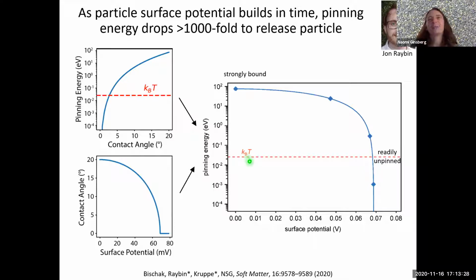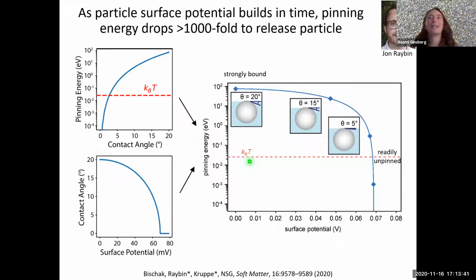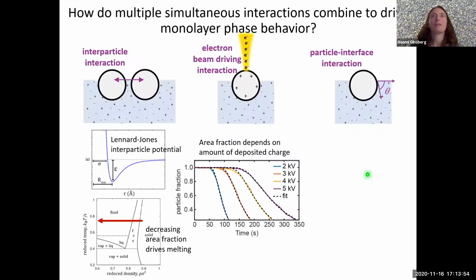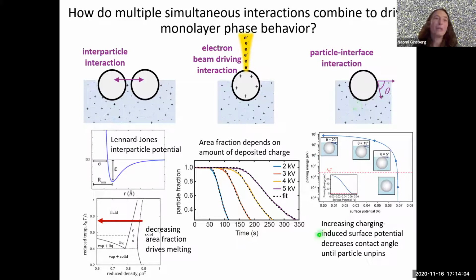And as the electron beam repeatedly scans over a given particle, the surface potential increases, drawing more ionic liquid to cover the exposed particle surface and decreasing the contact angle. And then at a certain point, the pinning energy is decreased so much so that it's comparable to this thermal energy, and it's readily unpinned, decreasing the area fraction. Okay, so by considering the interaction of a charged particle with the interface, what we have now deduced is that the increasing charging-induced surface potential decreases the contact angle of the particle until the particle just completely unpins.